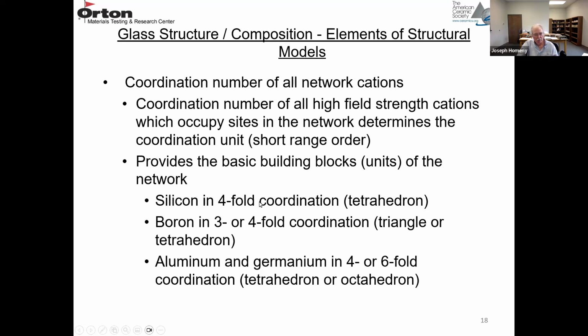So a silicon would be in four-fold coordination in this tetrahedron. A boron would be in three or four-fold coordination. If it's in three-fold coordination, it's going to form a triangle. If it's in four-fold coordination, it's going to form a tetrahedron. So silicon and boron are glass formers. Aluminum and germanium are glass intermediates, will form a glass in the presence of a glass former. They can be in four or six-fold coordination, either in a tetrahedron or an octahedron.